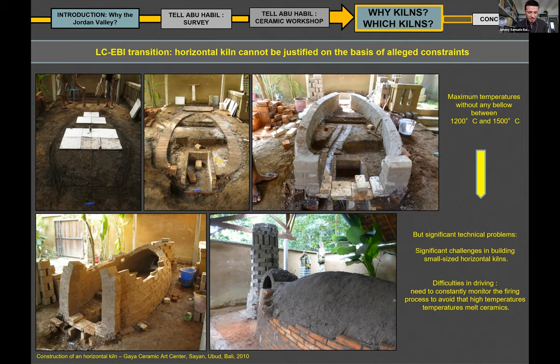Personally, I have attended and participated in only four experimental constructions and experimental firing sessions with this horizontal type of kilns, but ethnographic data and experimental sessions underline that, paradoxically, the remarkable technical features of these horizontal kilns very often end up being limited. Very serious limit, because the construction of small horizontal kilns is a very complex operation. The maintenance of horizontal kilns is quite complex, and the firing cycles require constant attention and intervention by the potter, so that the temperature does not rise too high and melt the vessels.